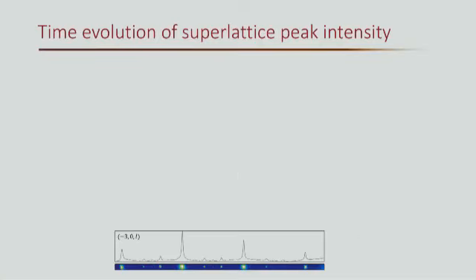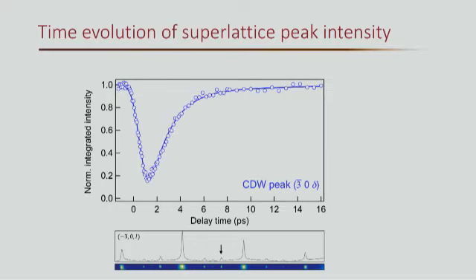So again, this is a static electron diffraction pattern, where the big peaks are the Bragg peaks, and these small peaks are the charge density wave superlattice peaks. You saw in the movie already that, for example, if you look at this charge density wave peak, it gets suppressed as we pump with the ultrafast laser. If you put that into a two-dimensional graph, here basically we're saying the integrated intensity of this peak decreases and then quickly bounces back.